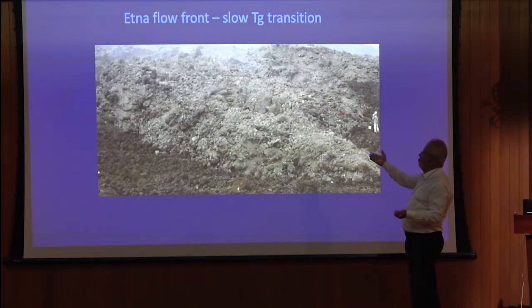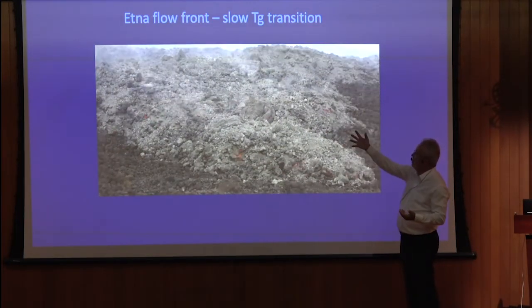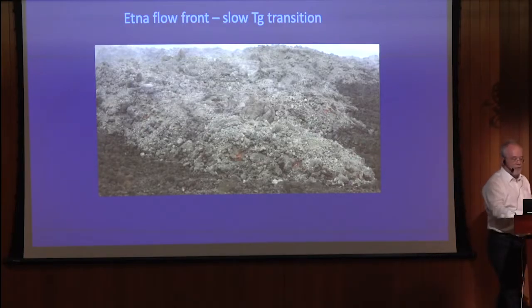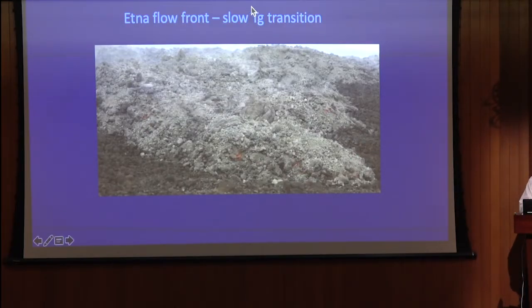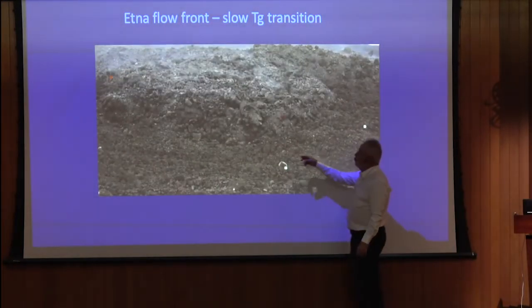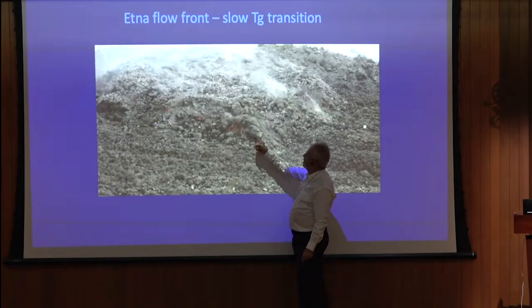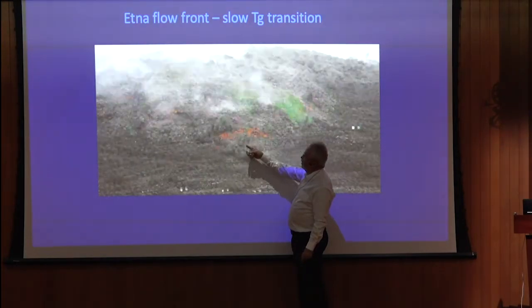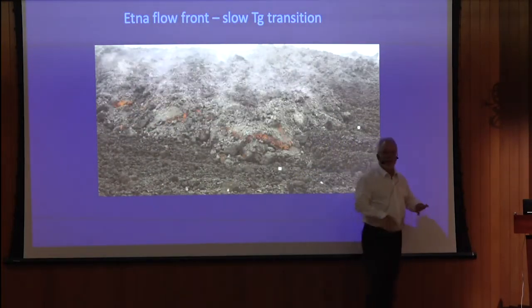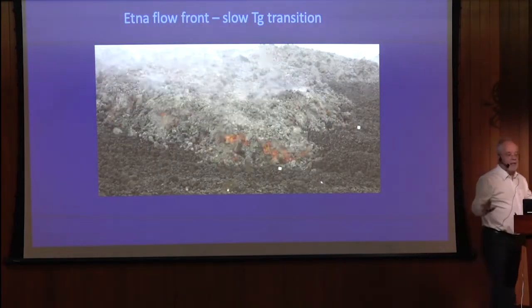And what you see is a lava flow, which is clearly ductile on a large scale. But of course, if you focus and you look at the blocks falling off the front of the lava flow, then you see individual cooled blocks are no longer ductile, or very little ductility. They are brittle. They're cracking, falling off the surface.